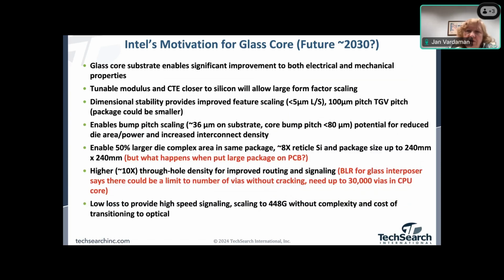So Intel's motivation for this glass, maybe they would get there by 2030 or so in a production type setting, maybe sooner, but that's I think a realistic time frame. The glass core substrate is going to give them this improvement for electrical and mechanical properties. They say it'll have a tunable modulus closer to the CTE of the silicon, dimensional stability so they can do these fine features, going much finer, enable the bump pitch scaling that's needed for the high density, high performance applications, larger packages. Maybe you could do a much larger package size.